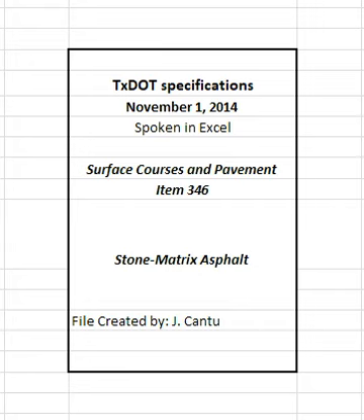Take immediate corrective action if the VMA value for any sublot is less than the minimum VMA requirement for production listed in Table 7. Suspend production and shipment of the mixture if the engineer's VMA results on 2 consecutive sublots are below the minimum VMA requirement for production listed in Table 7. No production or placement payment adjustments greater than 1.000 will be paid for any sublot that does not meet the minimum VMA requirement for production listed in Table 7 based on the engineer's VMA determination.